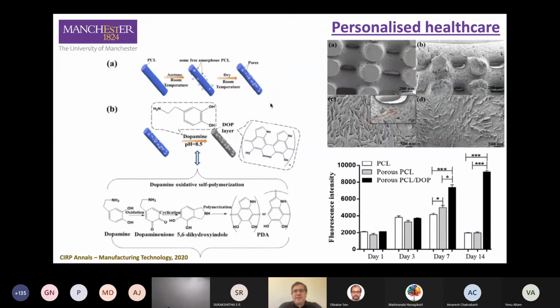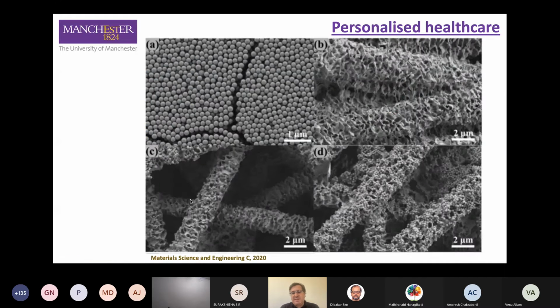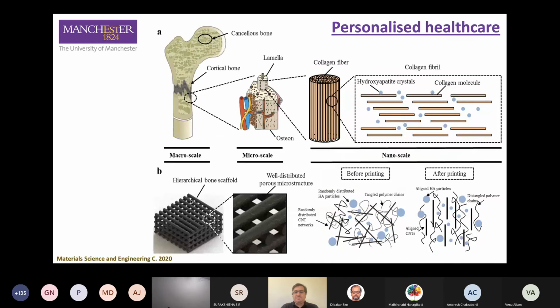In terms of surface modification, as I mentioned, we are developing several strategies. One is represented here: we use an acetone vapor annealing strategy to induce some porosity on the scaffolds, and then we dope the scaffolds with dopamine to improve their biological properties. Another strategy is basically to coat the scaffolds with nanoparticles of silica, again improving the mechanical properties and creating a very rough but controlled surface, which increases cell attachment and proliferation.